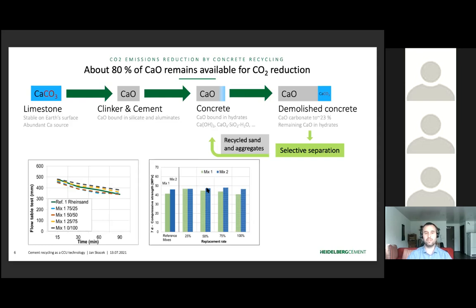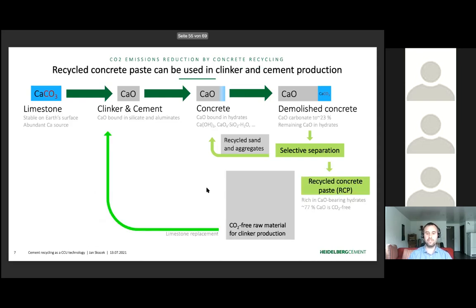This is a simple one-to-one replacement of virgin materials by the recycled materials. So this is the key contribution to circularity, to the preservation of natural resources. But the main CO2 saving is realized by the remaining fraction, the recycled concrete paste. As mentioned, this is rich in calcium oxide and almost free of CO2. So we can use it to replace the limestone in the burning process of clinker, which directly reduces the CO2 emissions, as we don't need to decompose that much limestone into calcium oxide.